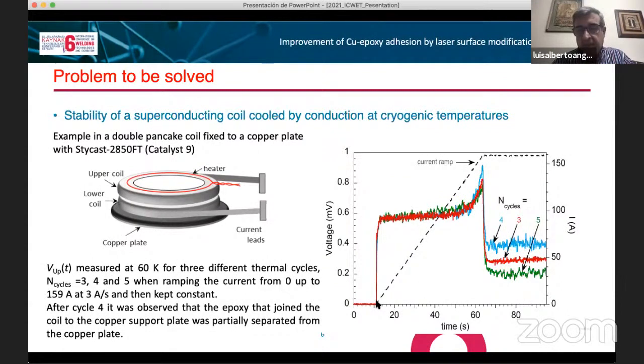Here in this curve, you can see the behavior of this coil when we apply a given current to the coil. When you are increasing the current, you have the typical induction voltage until you reach the critical current of the superconductor, and then the voltage starts to increase. And once you reach a constant value of the current, then you have the remnant voltage that you are generating on the coil.